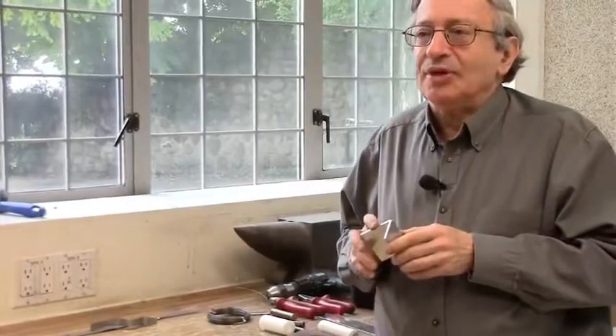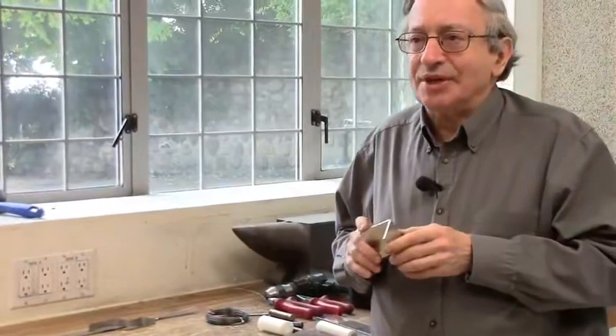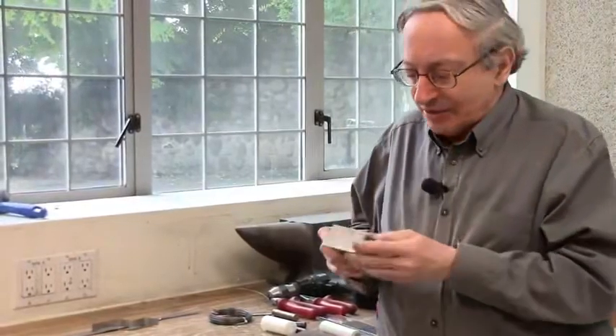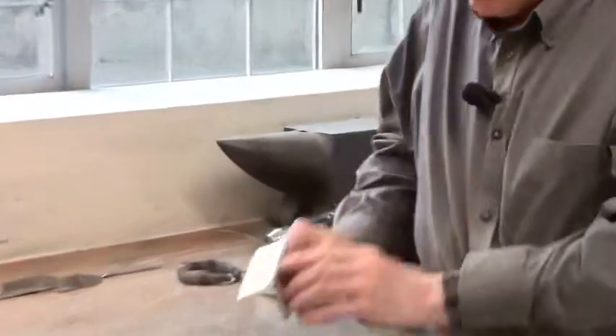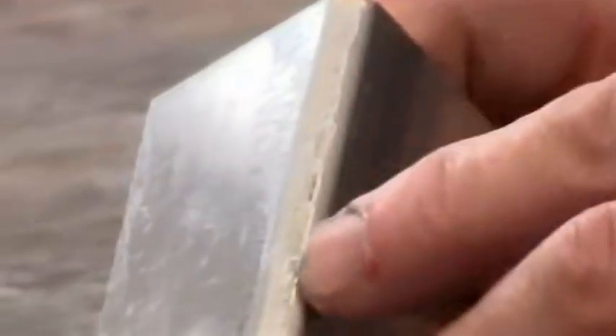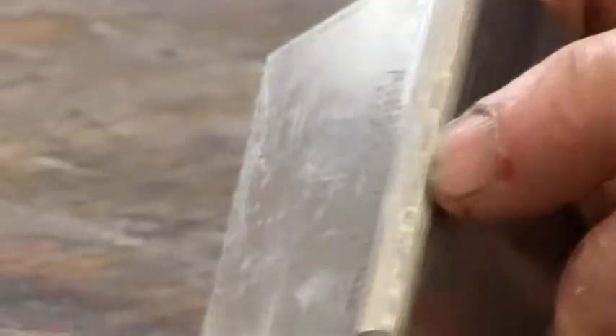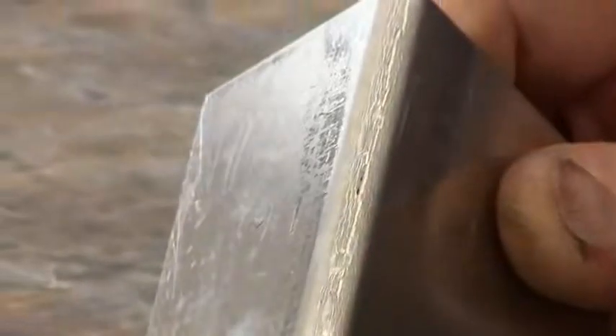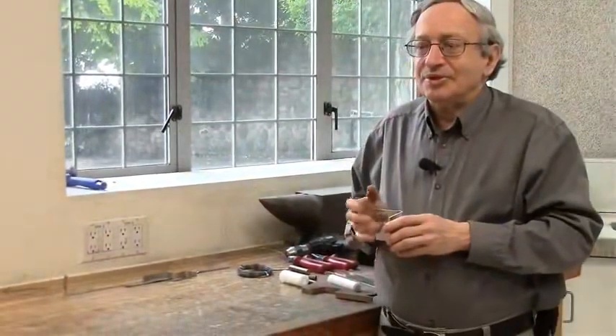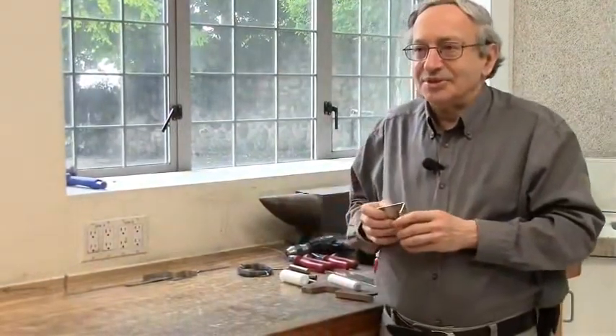The more popular alloy is probably 6061, but if you bend it, it'll crack. Now, I just bend this, and if you zoom here, you can see the crack at the bend. Since a lot of heat sinks have to be bent to increase the surface area, it's better to use 5052. So I wouldn't even bother stocking thin aluminum because, except for heat sinks, I don't see much use for it.